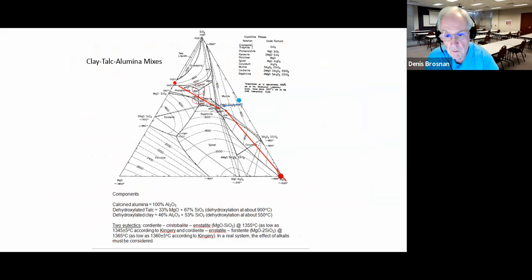Now, cordierite occurs naturally, but not in large scale deposits as a mineral. So typically we have to make cordierite. The high purity cordierite is made by taking mixtures of talc, which is magnesium silicate represented over here on the phase diagram. And we're going to take metakaolin here. Remember, that's dehydroxylated kaolin. And we're going to try to hit that composition.